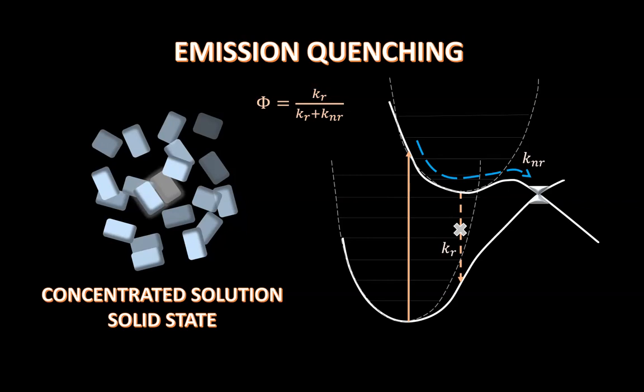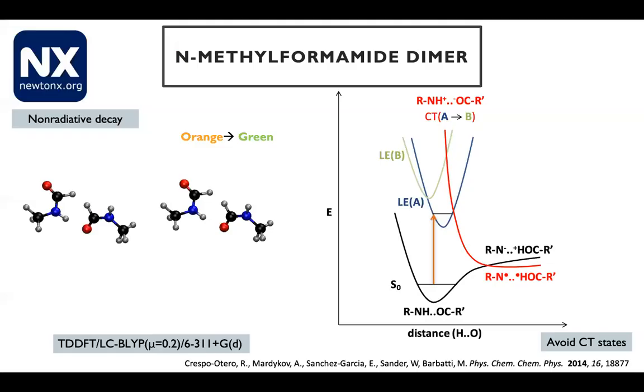Other processes that could happen are related to the formation of cavities in the solid that will restrict in a way the motion of the system. I just wanted to illustrate in the next slide some of these non-radiative processes, and in particular what you can have if you have a charge transfer state. Charge transfer states play a very relevant role in photochemical processes in the solid state because they couple with vibrations that in many cases are related to distances between the two molecules, and will take in many cases the system to the ground state.